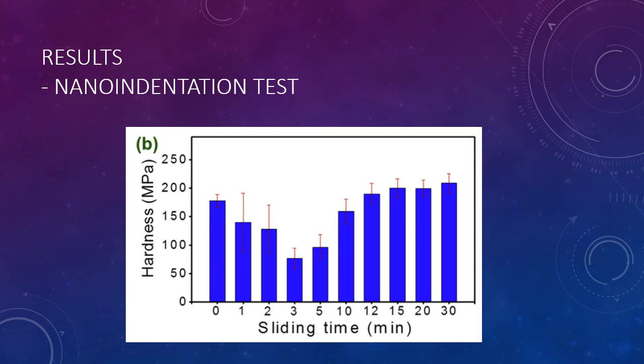For the nano indentation test, which measures the hardness of the sample, the authors carried it out at 0, 1st, 2nd, 3rd, 5th, 10th, 12th, 15th, 20th and 30th minutes of the sample. As you can see, although the hardness of the sample decreases at the beginning of the experiment, after 12 minutes the hardness of the sample is better than the initial one.